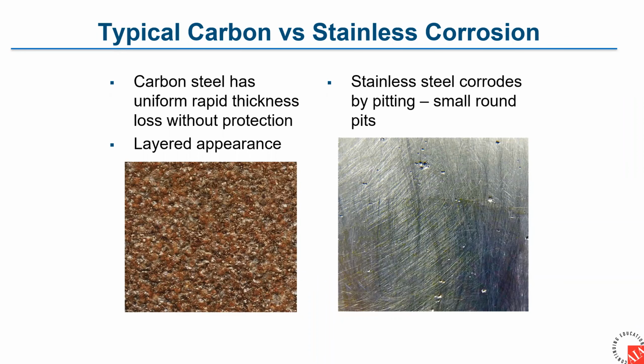Another aspect of corrosion resistance in particular is when carbon steel corrodes. If you've applied a coating but nobody has maintained it, then you get rapid uniform thickness loss without protection, and that can adversely affect performance. Stainless steel instead corrodes by pitting. And even if you happen to have pitting through the thickness of the stainless steel, you may still have adequate structural integrity for it to perform its role in the case of resilient design.